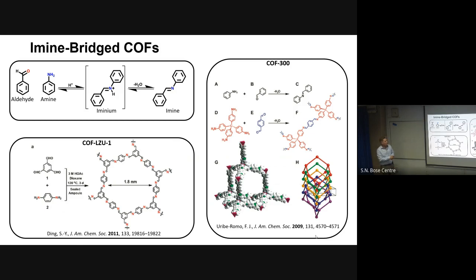So two examples that were reported early on are these 3D COFs. We have this tetraphenyl methane that helps generate such a diamond structure, and these anilines here are bridged with this aldehyde, forming a 9-fold interpenetrated network. And shortly afterwards, a 2D framework was discovered. It's called LZU-1, where you essentially use the same reaction in 2D. You have this trialdehyde here, you react it with phenylene diamine, and you get this very well studied LZU-1 imine-bridged framework.